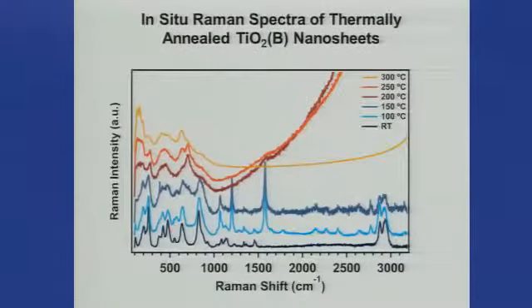The other thing that we could do is we could take the nanosheets in a flow cell in the presence of oxygen and heat them up and watch the Raman spectroscopy convert. What's shown here is basically at room temperature, we got something that looks, again, like the nanosheet morphology. As you start to heat this up, you start to see the formation of the nanoparticle structure, evidence of the sheet converting into a nanoparticle of TiO2B.